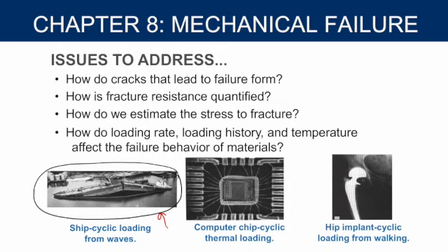It was made of a very strong, newer version of steel, an iron-based steel, but it hadn't been tested at cold temperatures. And so when the Titanic went on its maiden voyage up into the North Atlantic, where it was basically below freezing with the salt in the water, the water was still liquid, but it was below freezing in temperature. It made the metal quite brittle.